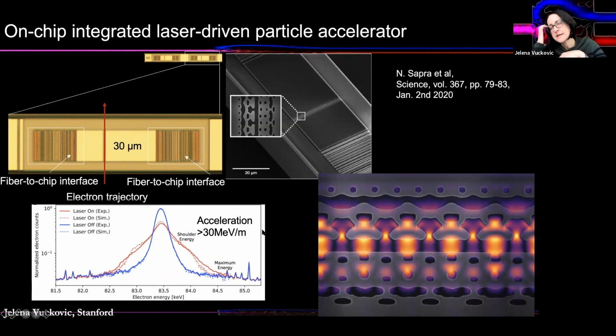Which, when you look at the gradient, and keeping in mind that this is only over 30 micrometers length, corresponds to acceleration gradients of more than 30 mega electron volts per meter. And that's comparable to really useful traditional accelerators. It also means that by cascading something on the order of a few hundreds or 1,000 of these elements, you can accelerate these electrons to mega electron volt energies, which is already useful for medical applications, for radiation therapy. And you can basically also obtain a concentrated beam of electrons that could be used for targeted radiation therapy in tumor treatments, instead of having a very large beam of electrons that also irradiates healthy cells and healthy organs.